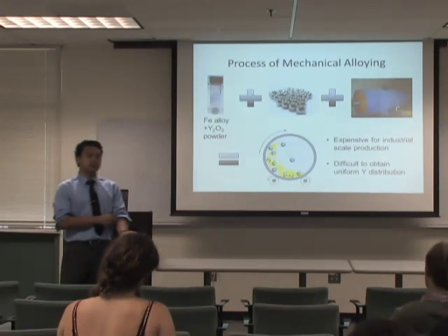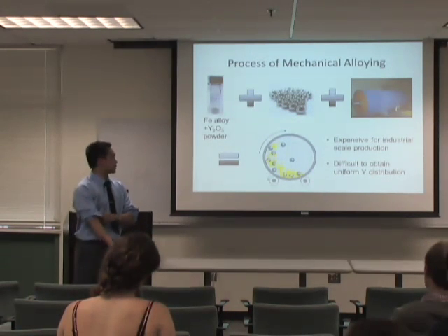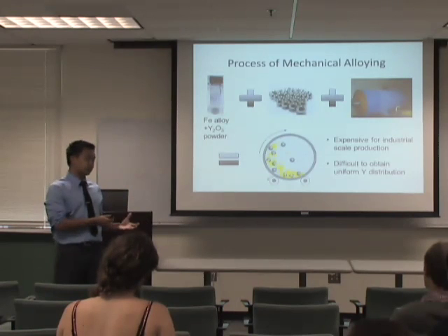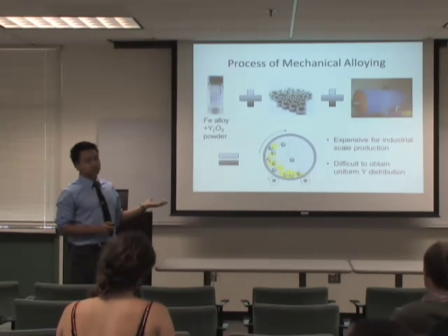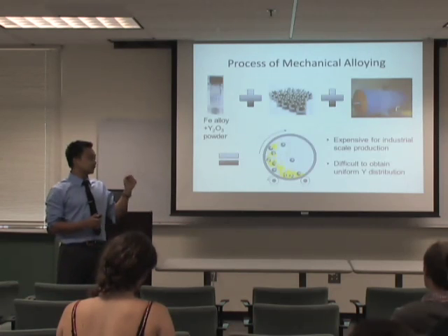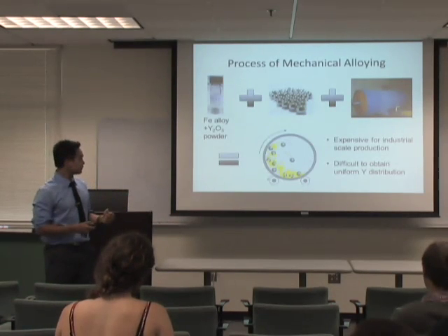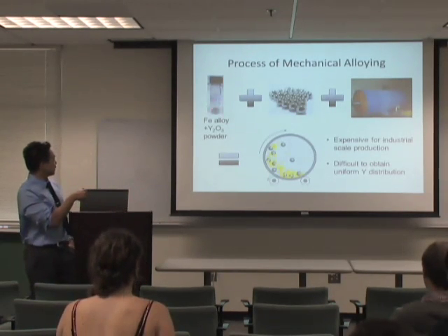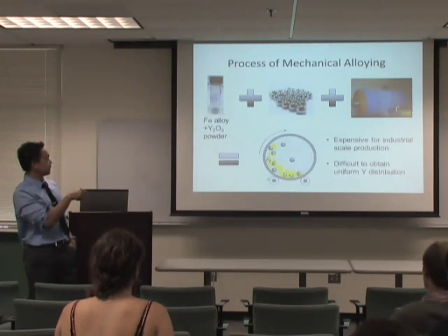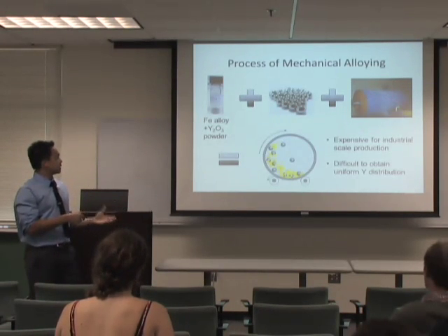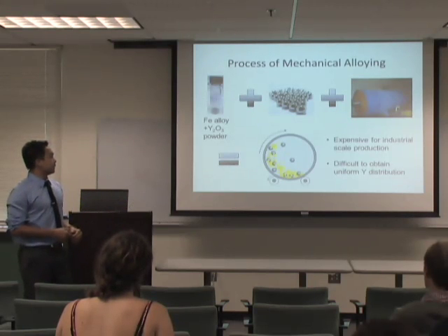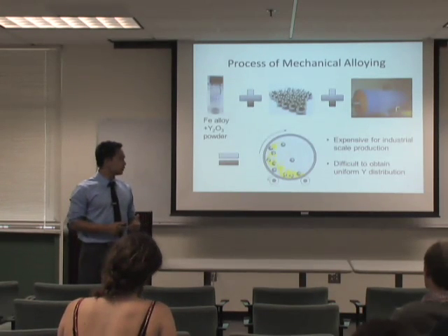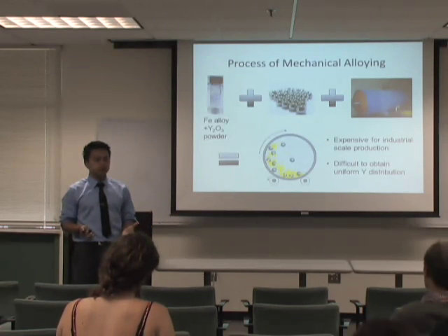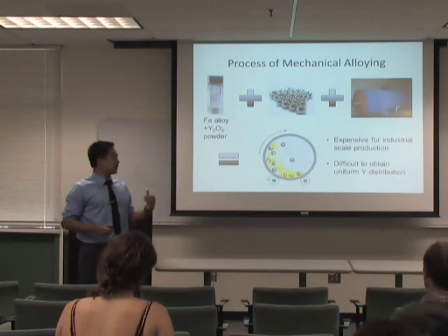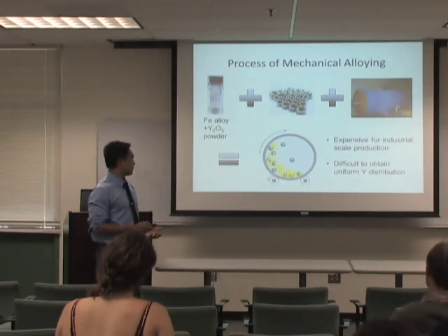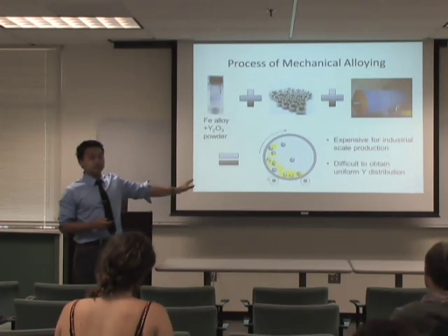Now, yttrium, one of the main components of our nanofeatures, is not soluble in iron, which is our matrix. So we have to use a process called mechanical alloying to physically force the yttrium into the iron. And this is done by mixing yttrium and iron powder with steel balls in either a roller or a mill to process it. Now, if I want to make 3 to 4 tons of this material to build a nuclear fusion reactor, it's going to be quite expensive and difficult to do. So we want to eliminate mechanical alloying.